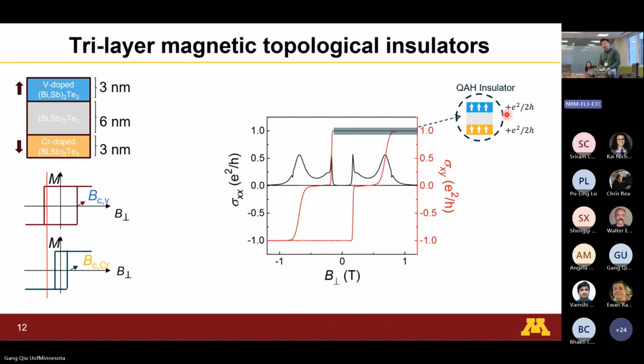Now, if we scan the magnetic field right here, we park it between the coercivity of the vanadium and chromium, you can actually put the system in this anti-parallel configuration. What this does is, well, each surface still gives you 1/2 of e squared over h, but they are in different directions. So they actually cancel out with each other. Okay, so this actually relates to a very exotic state, which is called an axion insulator.